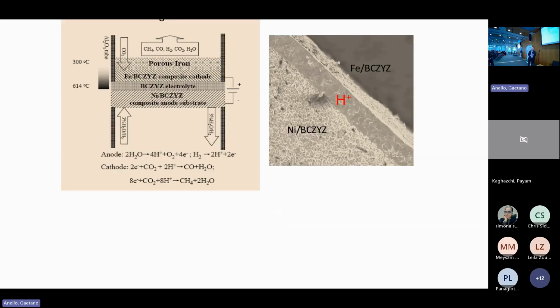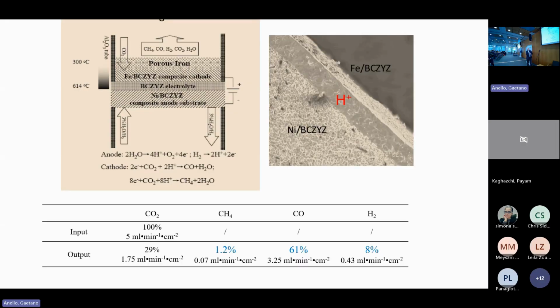If you go to a proton conductor, in a similar sort of experiment, you get more methane, and a lot of carbon monoxide. So the process changes. You reduce the steam to hydrogen. You actually end up promoting the carbon monoxide. It's often felt that to do CO2 conversion in co-electrolysis, you produce hydrogen, which then reacts with CO2. But in certain systems, you can do the CO2 directly. In this case, it seems preferable.